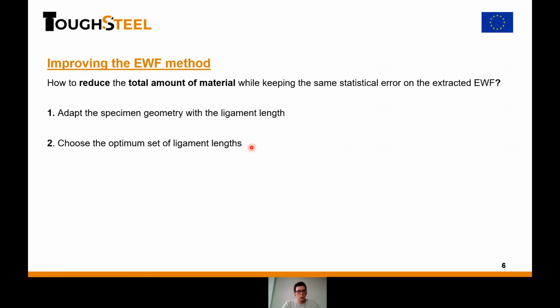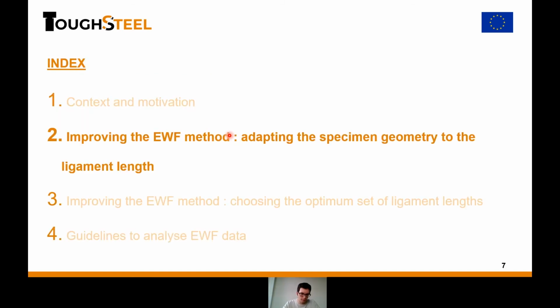So I will show you how I improved the method with the goal to reduce the total amount of material while keeping the same statistical error on the extracted essential work of fracture. I did it in two ways. The simplest way is just to adapt the specimen geometry to the ligament length, and the second one is to choose an optimum set of ligament lengths. So let's go over the first one.